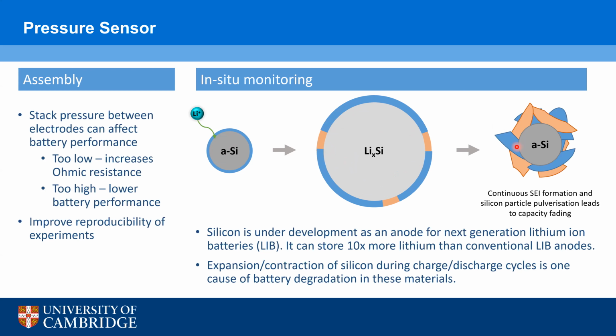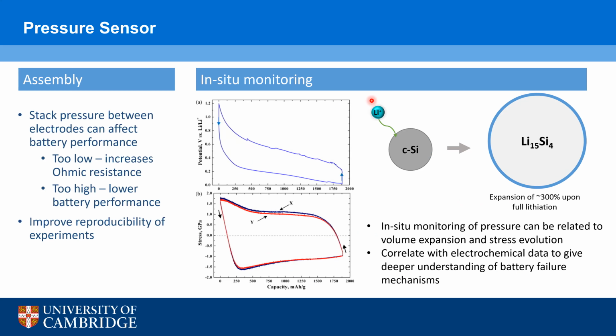And over multiple cycles, this expansion and contraction leads to continuous SEI formation, and this leads to the eventual pulverization of the silicon particle, which leads to capacity fading and the eventual failure of the battery. And so what we propose to do with the pressure sensing is monitor this in situ. During the electrochemical cycling, we can relate the measurement back to the volume expansion in the silicon, get an idea of the stress evolution within the silicon electrode, and then correlate that back to electrochemical data to give a deeper understanding of battery failure mechanisms.